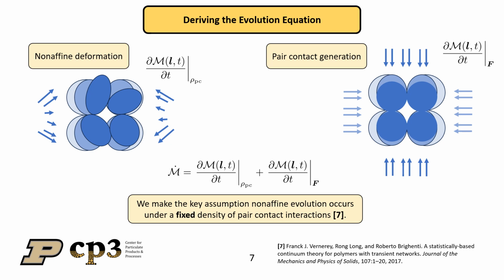We specifically propose two terms where each aspect is held static, namely one term that captures the non-affine deformation of the microstructure given a fixed set of contacts, and then another term that captures the evolution of pair contacts given a fixed global deformation gradient. The key assumption made in this representation of the evolution is that non-affine evolution occurs under a fixed density of pair contacts, and we will show the benefit of this assumption in the next slide.